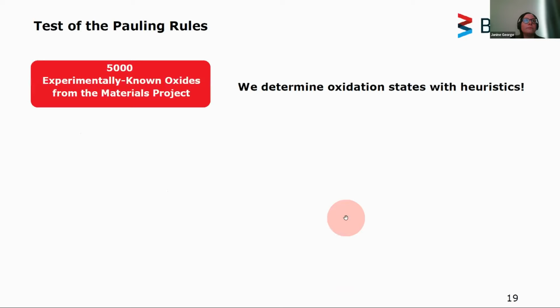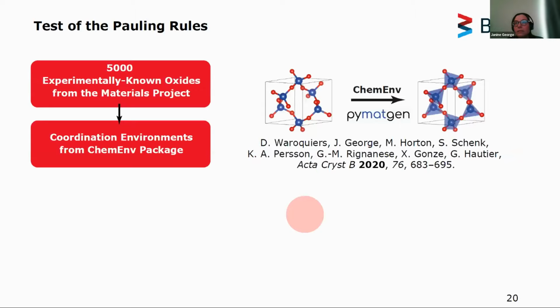So we then tested these Pauling rules. We took 5,000 experimentally known oxides from the Materials Project, determined the oxidation states with a certain heuristic, then used a tool that's called ChemEnv that is implemented in Pymatgen to determine the coordination environments.